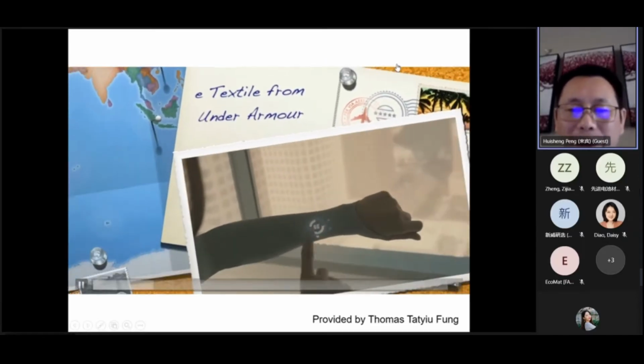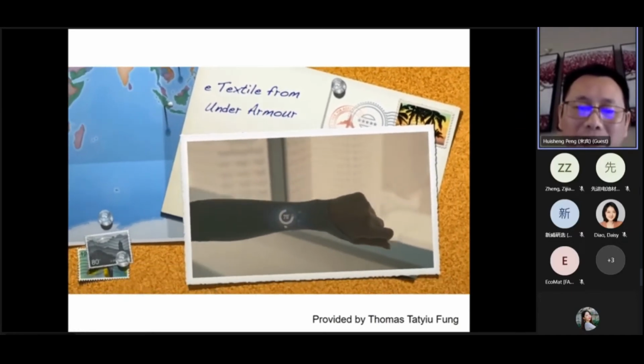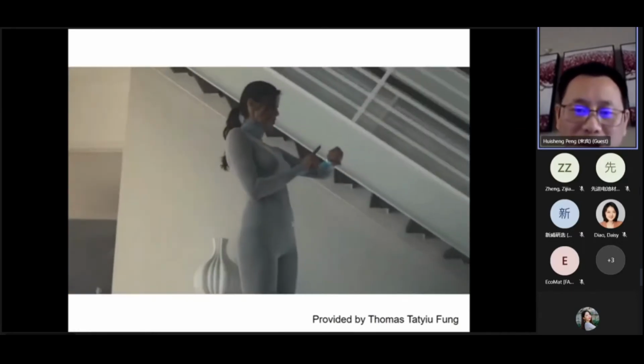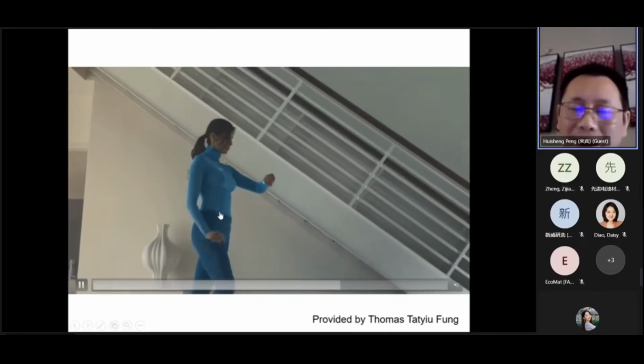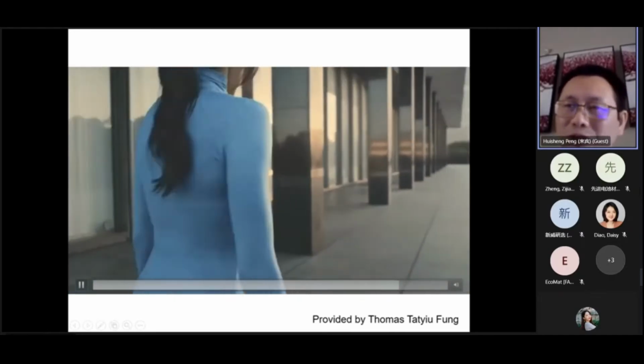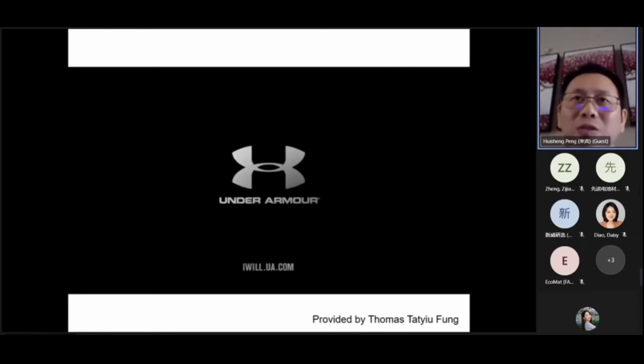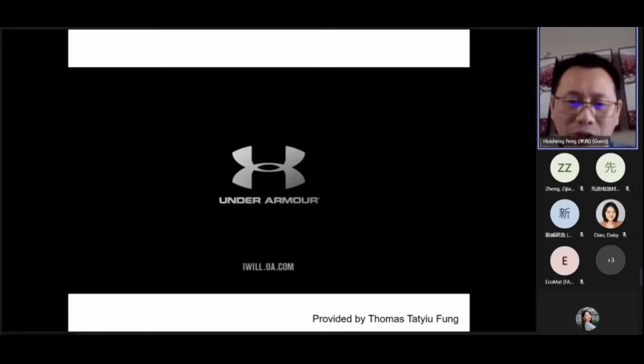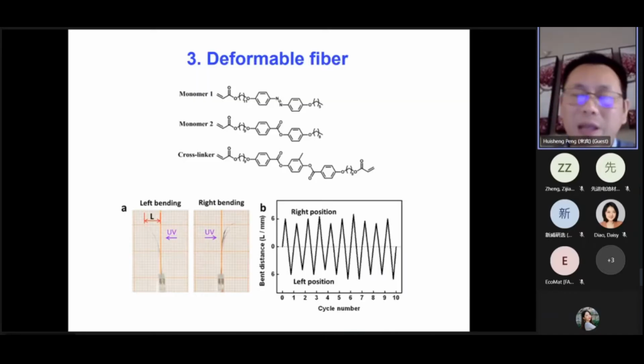Anyway, for this composite fiber, very interestingly, we can use just 5 volts to induce the color change. So they can be made into clothes, and clothes can change colors to show different patterns. So you can have different styles of clothes. In the future, possibly the fashion shops may disappear, because based on just one piece of clothing, you can get what you want. This is a very interesting direction, and we are commercializing these materials. The next is about the deformable composite fiber.